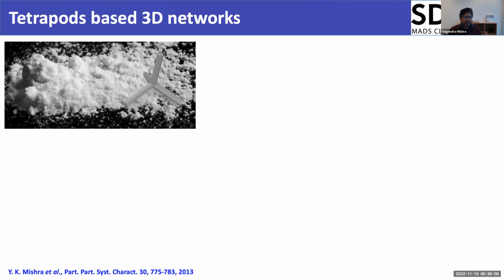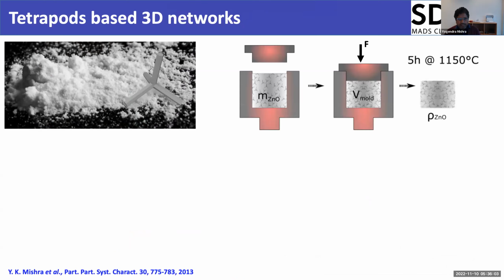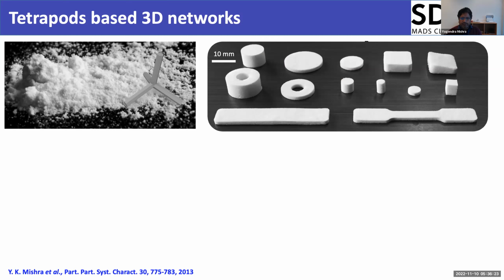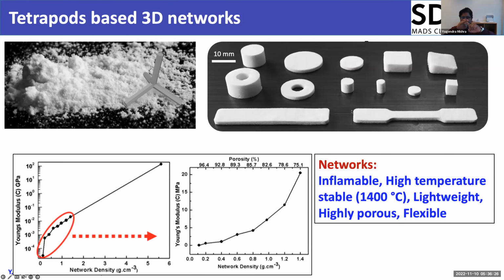And then, how do we make a sponge out of this? We take this tetrapod material, fill the powder into a mold with a well-defined volume, an amount we decide, and we press up to the defined volume limit. Afterwards we heat the tablet at high temperature, 1150 degrees centigrade for 5 hours. What happens due to the heating is that at the places where they are touching, due to diffusion, there is a formation of junctions, and we are able to produce these three-dimensional network tablets, which are made out of zinc oxide material. And the novelty in these tablets is that they have a porosity of around 95%.